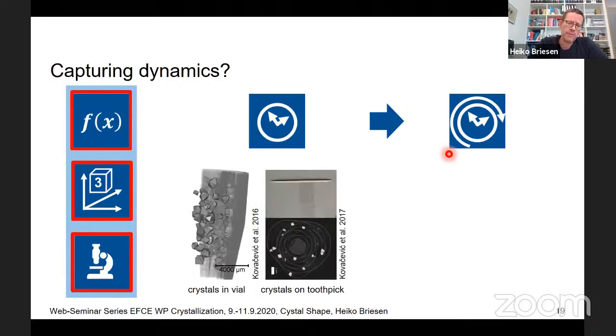So this was our sample preparation in the initial phases of the project. We just threw the crystals into some vials and did this characterization. I'd love to say that we have been more sophisticated than this, but this was actually really just a simple toothpick with an adhesive tape, and we basically crumbled the crystals on this adhesive tape and then wrapped the adhesive tape around the toothpick. And this is then a scan you see from that. Why did we do this?